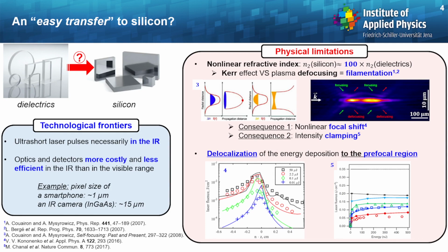And this regime has basically two major consequences. The first one, illustrated here on the left, is a nonlinear focal shift. As you can see here, when you increase the input pulse energy, the focus is shifted upstream towards the laser. And the second consequence is intensity clamping, meaning that when you measure or simulate the maximum fluence you can deliver in the bulk of silicon, or in the bulk of the material, as a function of the input pulse energy, then at some point it will saturate. And when you take those two consequences together, one can simply conclude that there is a strong delocalization of the energy deposition, preferentially towards the pre-focal region.